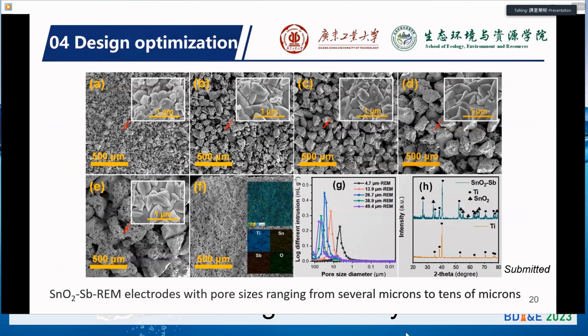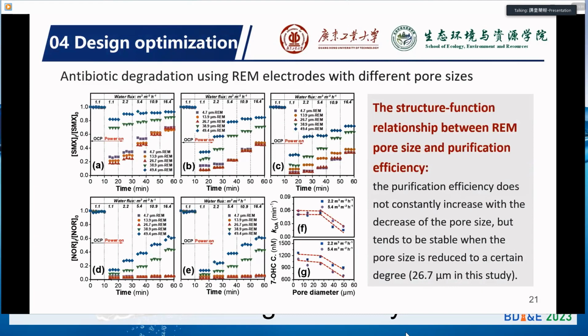So next, we think about how the findings from the non-uniform polarization affect the design of the electrodes, whether we can reduce the material consumption or optimize the whole design. We prepared a few antimony-doped tin oxide REM electrodes with pore sizes ranging from several micrometers to tens of micrometers, and tested their performance for antibiotics degradation.